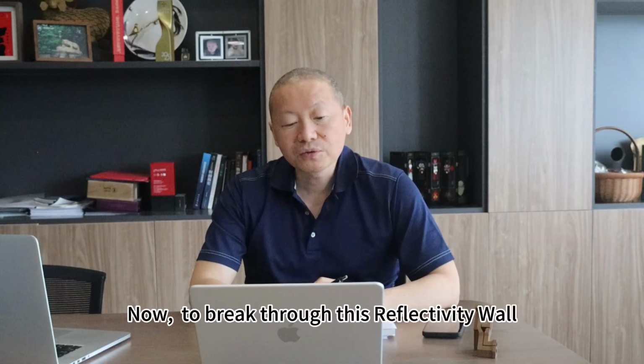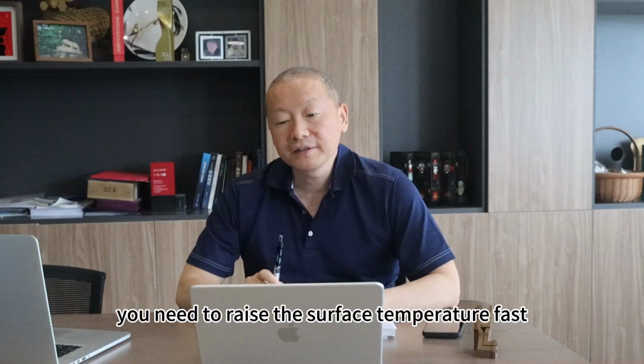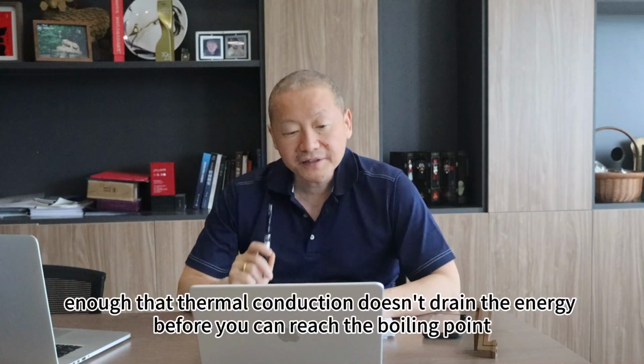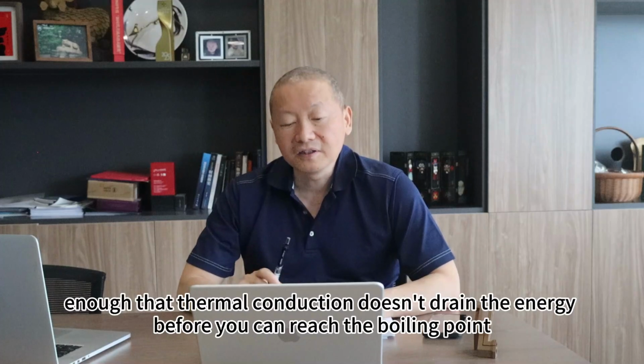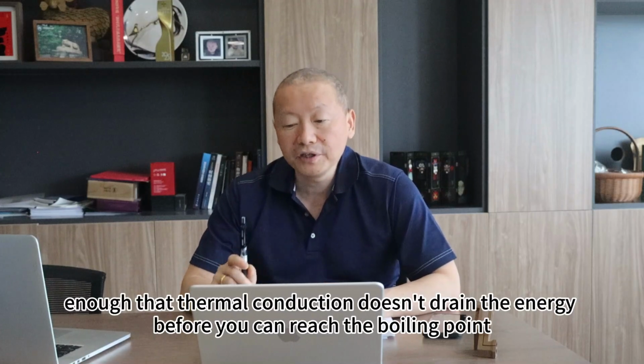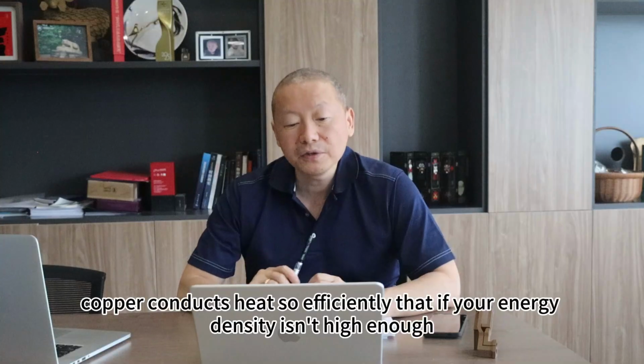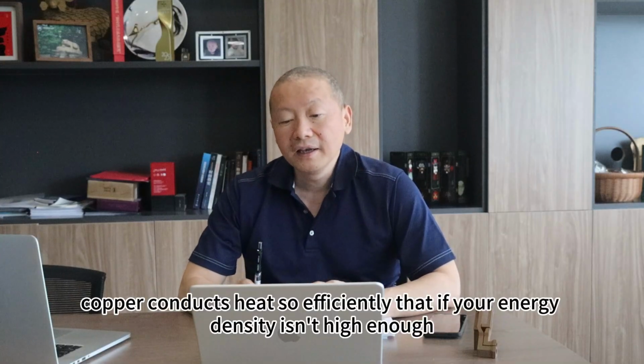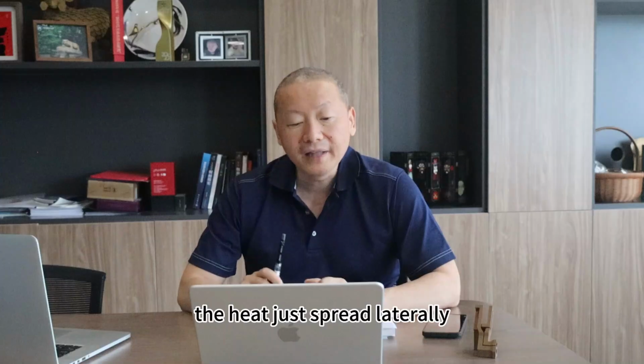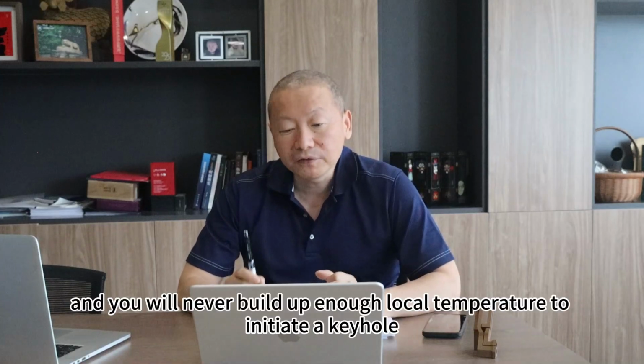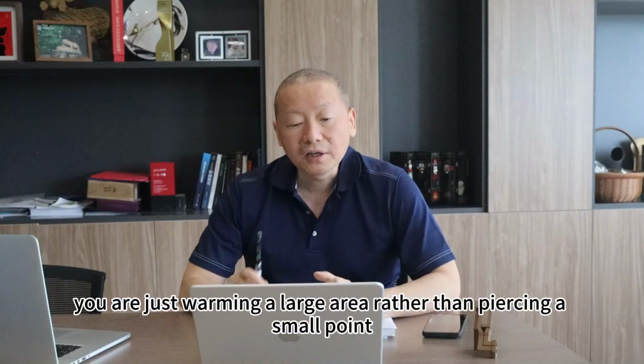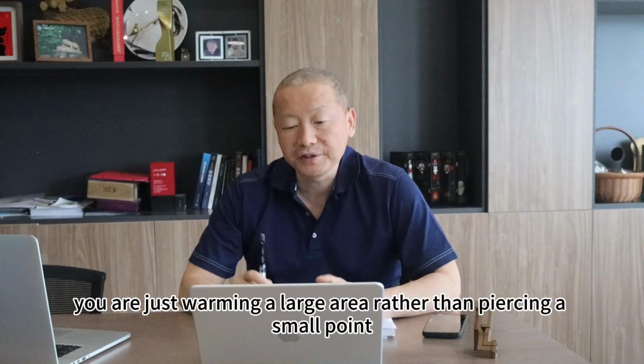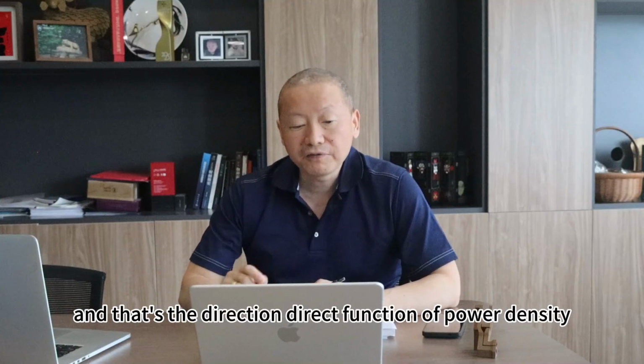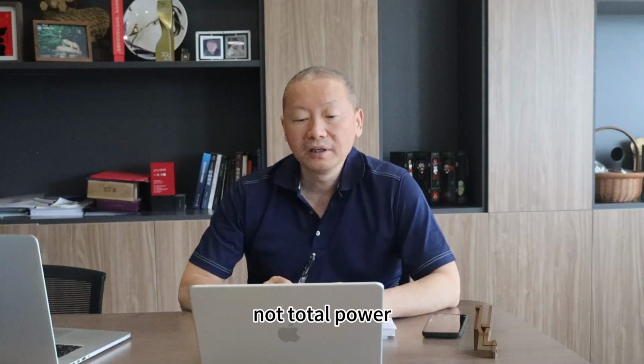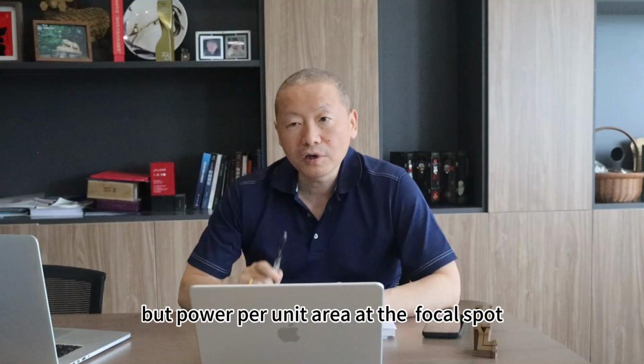Now, to break through this reflectivity wall, you need to raise the surface temperature fast enough that thermal conduction doesn't drain the energy before you can reach the boiling point. Copper conducts heat so efficiently that if your energy density isn't high enough, the heat just spreads naturally, and you will never build up enough local temperature to initiate a keyhole. You are just warming a large area rather than piercing a small point, and that's a direct function of power density, not total power, but power per unit area at the focal spot.